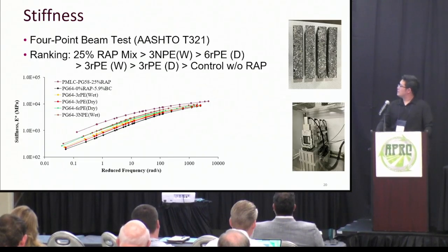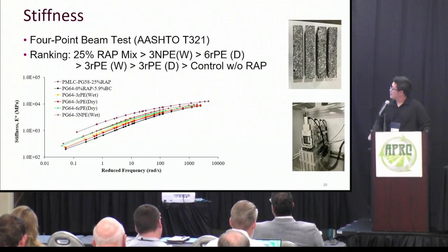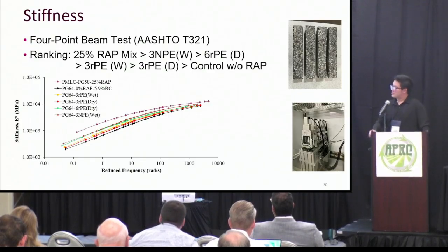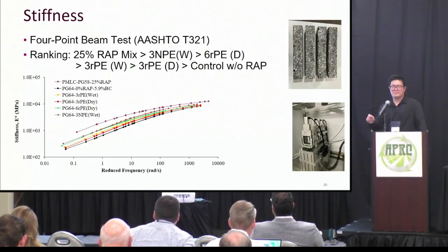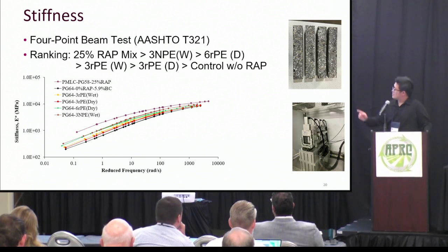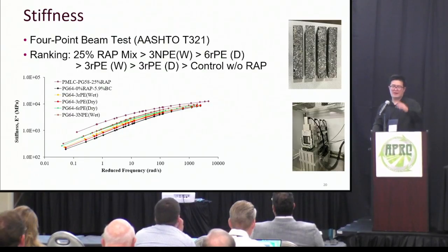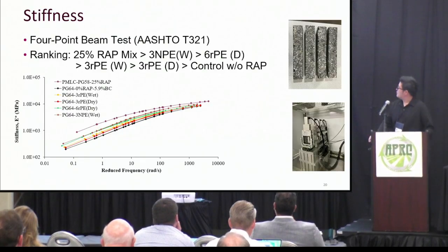And then we did the 4-point beam test to figure out the stiffness of the mixture. So let's say the ranking: the 25% RAP mix had very high stiffness, the control mix has the lowest stiffness, and the plastic modified asphalt mixture is in the middle.